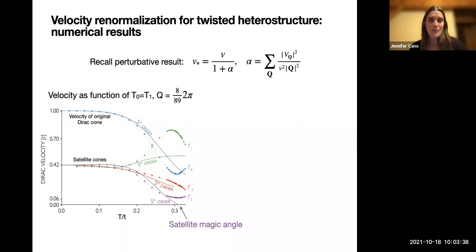So if you break time reversal symmetry, then these gapless satellite cones can become gapped. And if you add superconductivity, then you'll open a gap at half filling. So I would expect that both of those things can open a gap. And a person might ask, does the nature of that gap also change the density of states in some favorable way? Probably yes, because anytime you open a gap, you're further flattening out the bands.